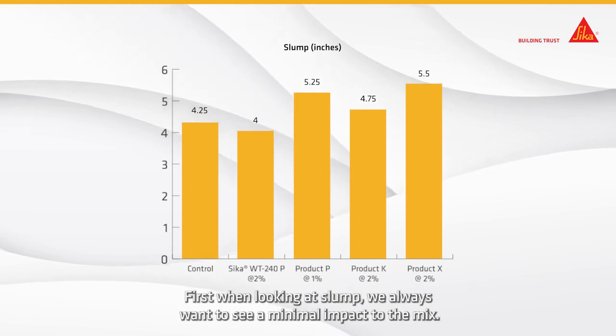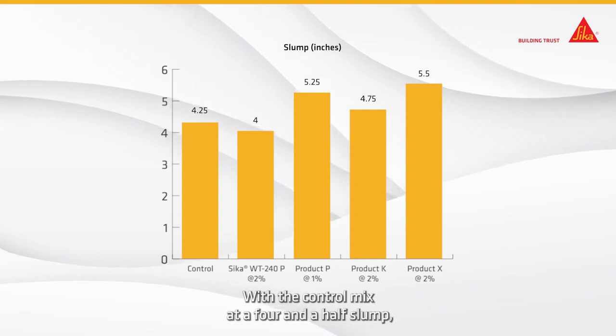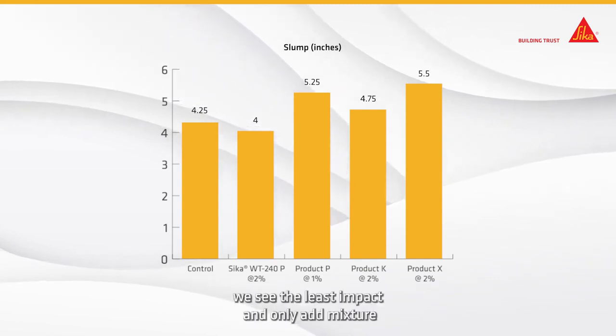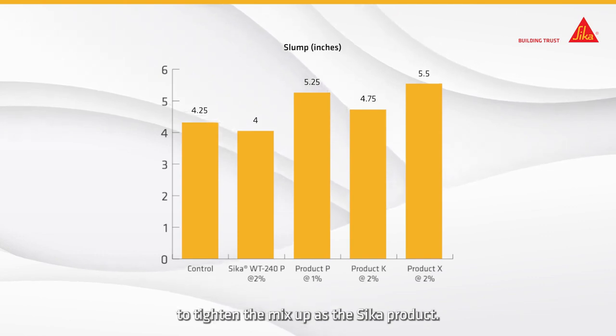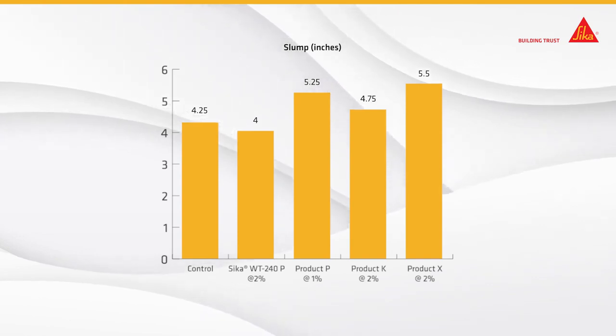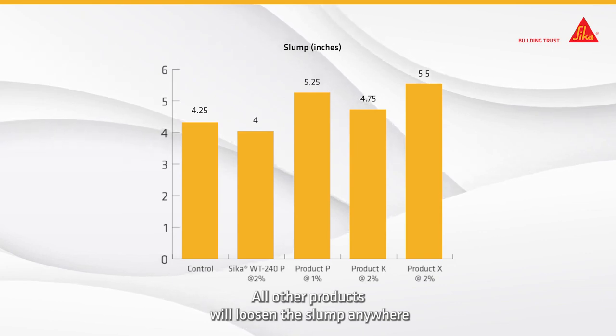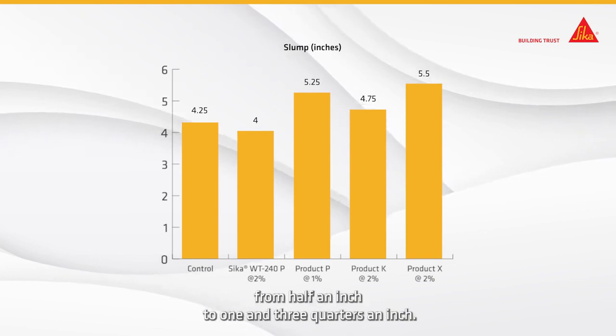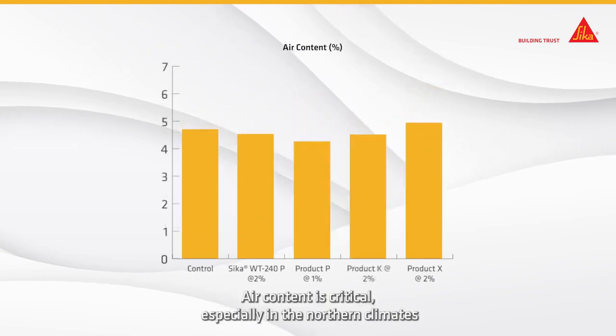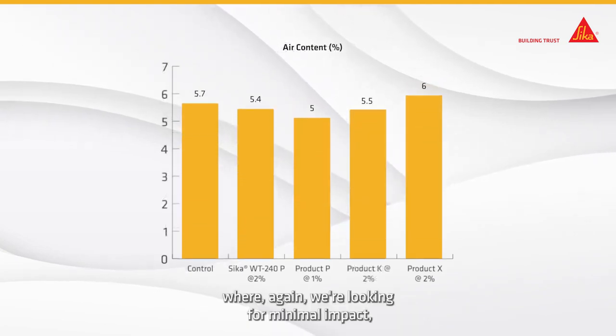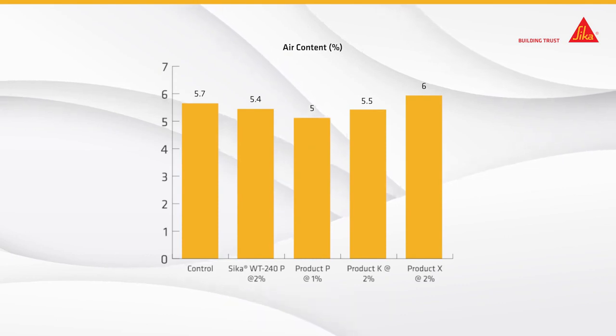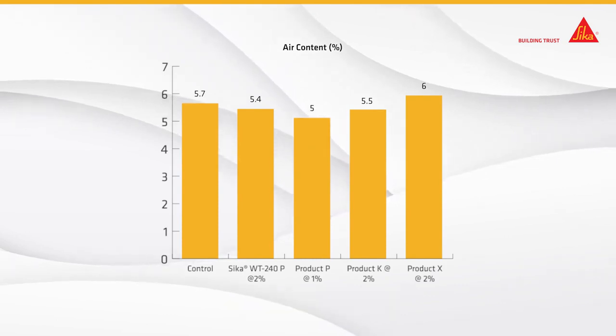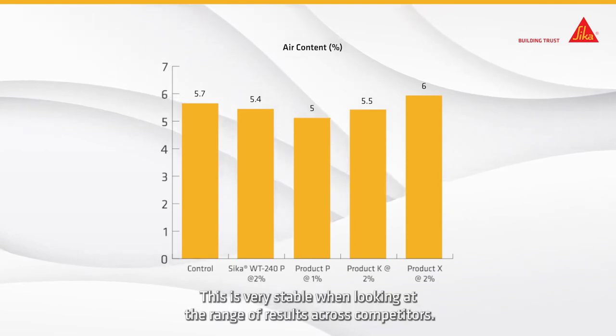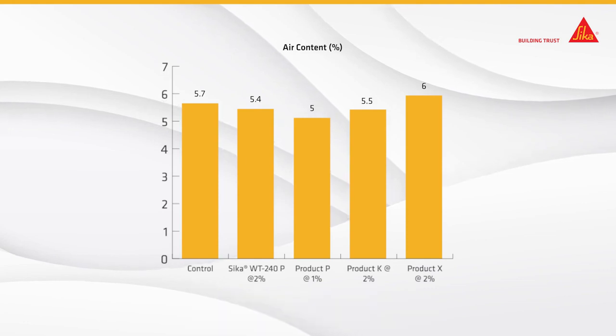First, when looking at slump, we always want to see a minimal impact to the mix. With the control mix at a 4.25 slump, we see the least impact, and the only admixture to tighten the mix up is the Sika product. All other products will loosen the slump anywhere from 1/2 inch to 1 1/4 inch. Air content is critical, especially in the northern climates, where again we're looking for minimal impact, and as we can see, the Sika product delivers a 0.3% decrease in air content. This is very stable when looking at the range of results across competitors.